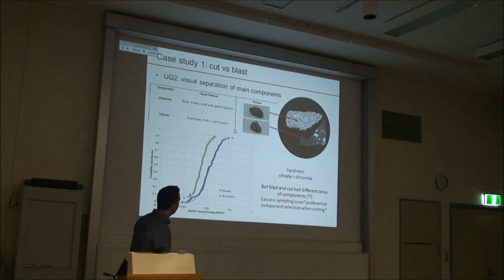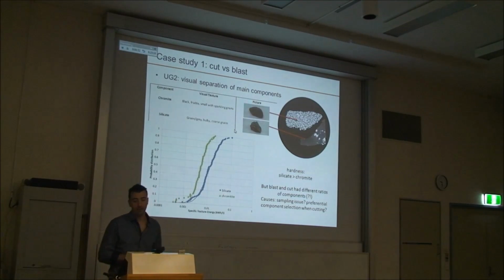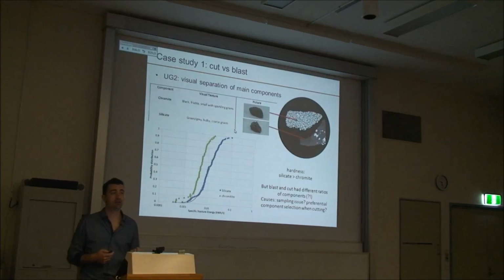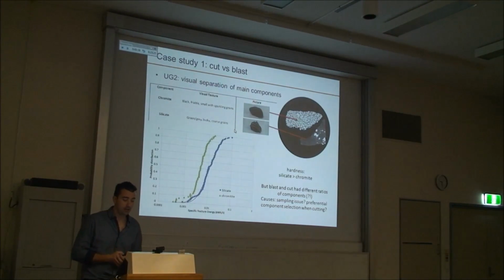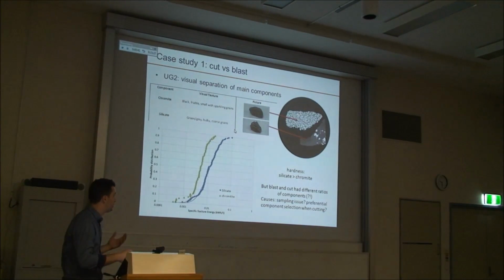We had a look at the tomography. So the first phase was chromite particles, and the second one was more silicate phase. And you can see there, the chromite grains are the bright little grains in this picture, and those particles are actually quite soft. They break easily, and you can find them in different ratios in the ore.